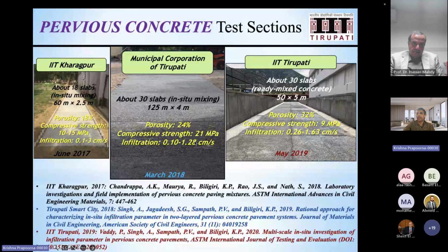So M10 to M20 concrete is what we targeted, for low volume roads. But the infiltration, or what we call the permeability, was very high. So if you talk about these numbers, they can be translated to about 70,000 millimeter per hour. That's the permeability that you get with these kinds of products, but they recharge very well. They recharge the groundwater. They are also very strong for low volume roads. Okay, you can run even a JCB on these.